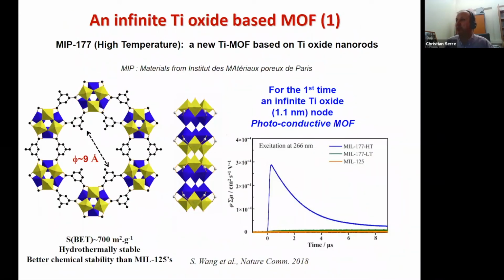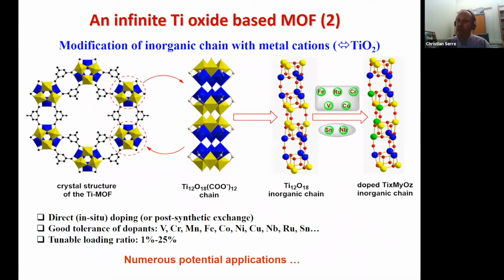In our case, a few years ago, we reported a titanium carboxylate MOF that was photoconductive because you have these infinite titanium oxide nanorods as a building unit. So this was demonstrated by TRMC, where you have a lifetime of the separated charge that is evidenced for a few microseconds. While if you take cluster-based MOFs, there is almost no charge separation. And then what we did, we decided to use these titanium oxide nanorods and dope them with different metals in order to tune the catalytic properties.